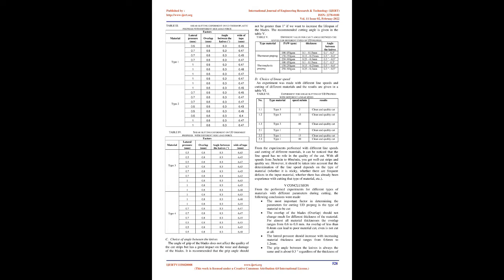The quality of the cut strips for UD thermoset and thermoplastic tapes is influenced by several factors, and the most important can be singled out: cutting angle, determining the overlap of the blades, determination of lateral pressure, the sharpness of the knives, the material and shape of the knives, as well as tension control, tension in the system, and line speed control. The standard width tolerance for cut strips commonly used in automatic fiber laying technology is from +/-0.125 mm to +/-0.127 mm. 3. Results and discussion.